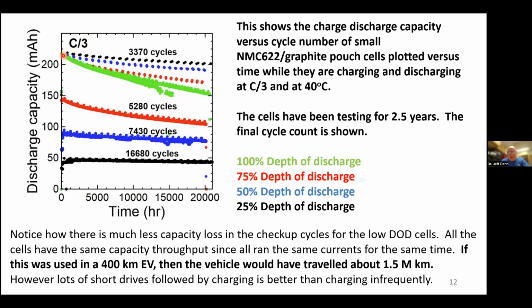Green are cells that are undergoing 100% state of charge range, or 100% depth of discharge. In red, 75%, in blue, 50%, and in black, 25%. And you can see the number of cycles that have been accumulated during this 20,000 hours of testing, a large number of charge-discharge cycles.